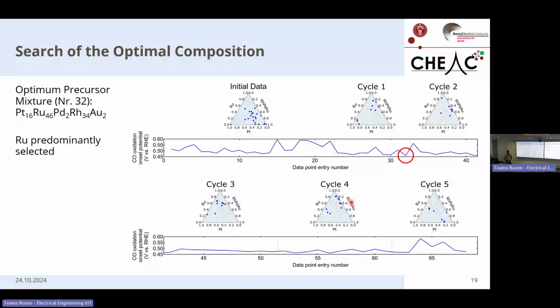Also, because I'm now working in the lab, I am often limited by waiting processes that are beyond my control. If I have to dry a sample, I have to dry it for a day, and I cannot accelerate it by using a fan. So the Bayesian optimization was used to suggest batches of experiments so they can be executed in parallel. And we see that in the first cycle, so in the first batch, we already find the global optimum, which has a precursor mixture predominantly composed of platinum, ruthenium, and rhodium.